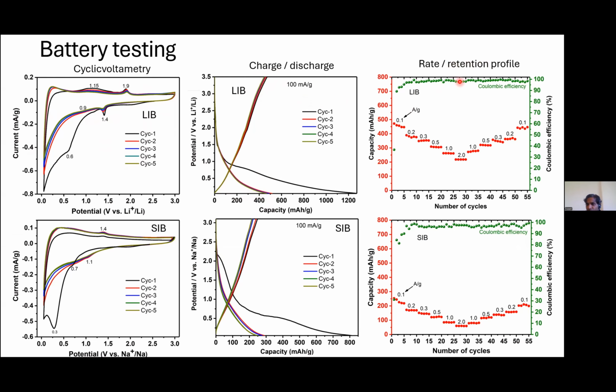And the third important test is rate retention analysis, in which what we do is firstly we test with a smaller current density, in this case 100 milliampere per gram. Okay, and then slowly you increase the load, that means increase the current density, and reach a maximum current density. When you give more and more load to your battery, obviously the capacity will be different. I mean, it decreases. And the important thing is that when you go back, when you systematically reduce the current density step by step, it retains the capacity it had before. The best battery does it. So by seeing this, you can understand that this is a very good battery, really a good battery.